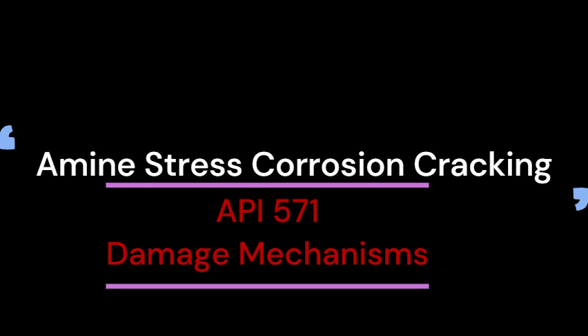This is where it gets really practical for inspections, right? This cracking isn't just random, it shows up in very specific places. Depends heavily on how the steel was treated, you said. That's exactly right. It comes back to that stress relief, or rather, the lack of it. Yeah. The vast majority of amine SCC failures happen right at or very near non-post-weld heat-treated carbon steel welds. We often just say non-PWHT welds. Because the welding process itself leaves behind those high residual stresses if you don't heat treat it properly afterwards. Precisely. As the weld cools and contracts, it creates intense localized stress fields. Without PWHT to relax those stresses, you've basically set the stage perfectly for cracking if the amine chemistry is right.